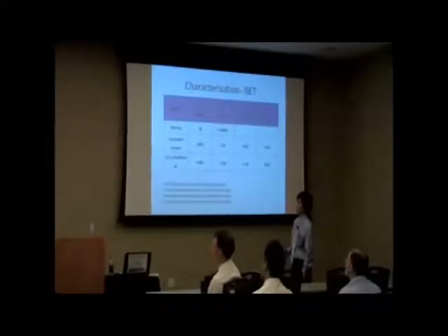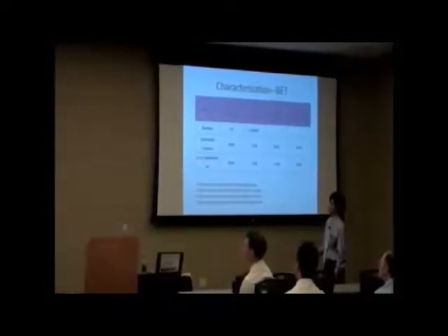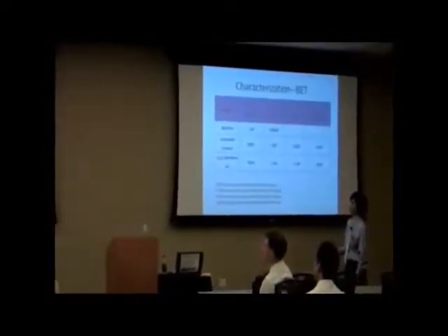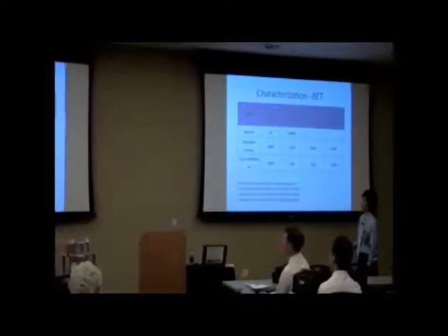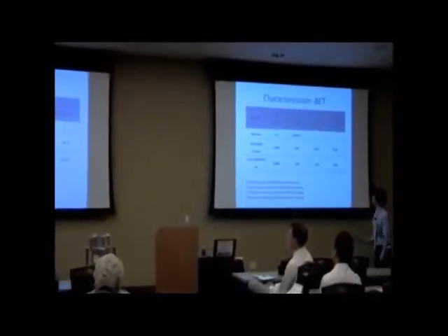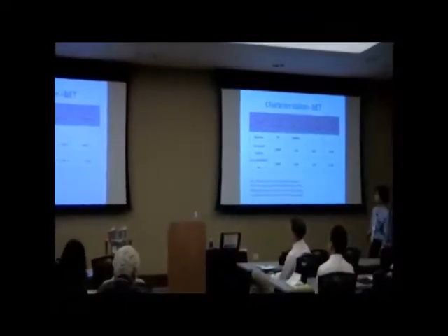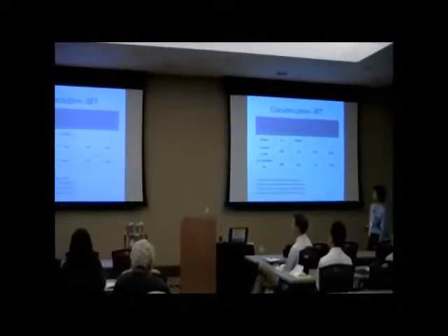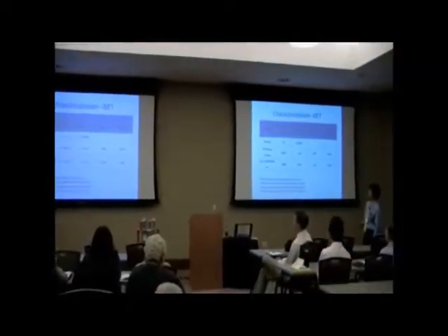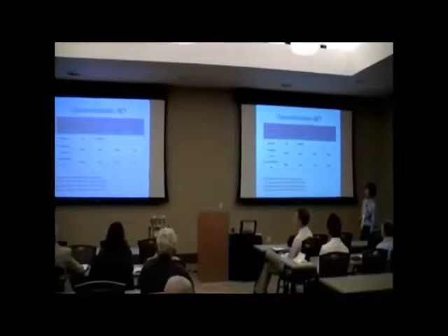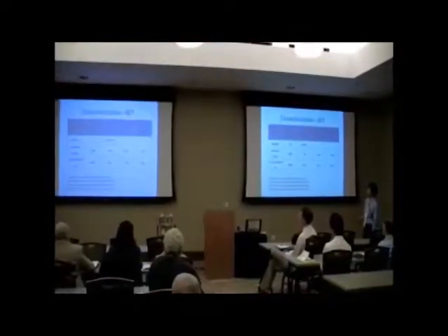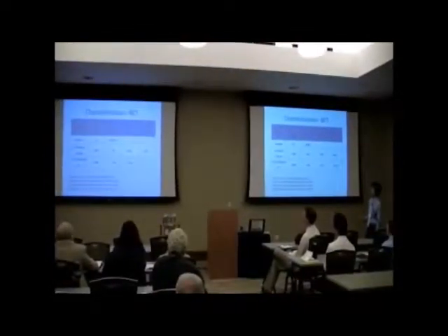For the biochar, as you can see, it has a very low surface area. But for the active carbon, it goes up to more than 100 times that of the traditional biochar. And the volume is also very high. For the macropore and mesopore, both are very high.